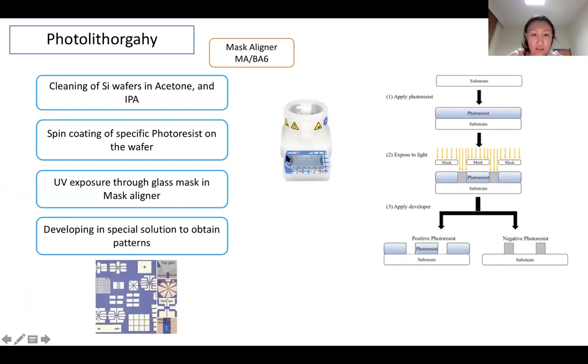Also in our laboratory, first of all, you start with cleaning your silicon wafer with acetone and isopropanol. This is very critical because even a tiny particle, like a 1 nanometer particle, can destroy your device, and your transistor will not work. So the important stage is cleaning. Then using this machine, called a spin coater, you put photoresist on the substrate. Photoresist is a special polymer, and as I said before, it is sensitive to ultraviolet light. And then after you spin coat, the spin coating also has different parameters like the speed of your spin coating, then time.